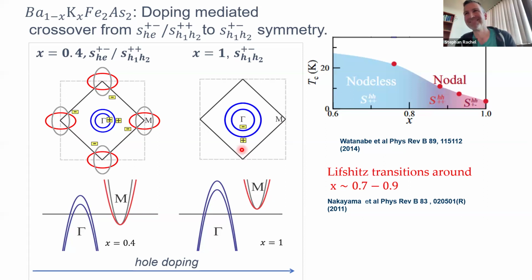It's just so confusing because, just for the experts, I can mention that for some time my understanding was that after the P wave, or triplet superconductivity, had been excluded, the simplest plausible explanation was put forward by Jörg Schmalian and collaborators, where they said this is accidental degeneracy, which is further bound by the presence of dislocations, which act as a seed to have this accidental degeneracy with time reversal symmetry breaking.